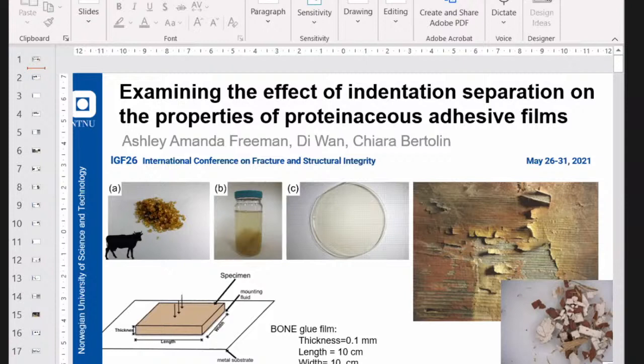So what we did is that we made glue, or an adhesive, from bone of a cow, and then we adhered that to a metal slide, which you can see in a schematic in the lower left-hand image. The entire idea is that when we are indenting, we would like to see how many indents we can get in one area without affecting the actual obtained modulus or hardness values.